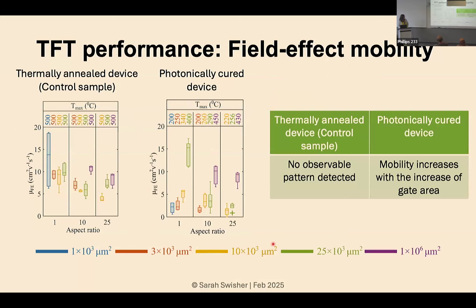Whereas the photonically cured devices show exactly the trend that we would expect, where as you go up in area from blue, red, yellow to green, we see a corresponding increase in that field effect mobility, which helps us to see that, yes, the simulation that we did was valid. And indeed, there is clearly a difference in the material for these different devices, where the only difference is the size of the gate. The channel dimensions of the transistors were actually the same for all the devices.